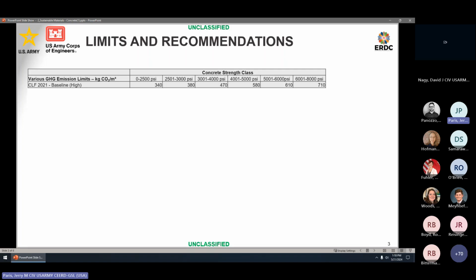So if we look back at the Carbon Leadership Forum for 2021, this generally makes sense. If you're looking at it, as the concrete strength goes up, you typically need more cement. So your limits tend to be higher with the higher strengths, and that generally makes sense. And in this document, they noted that they are treating a baseline as a static reference against which to compare progress towards a goal, which is exactly what we want, right? We want a baseline value, right? Because ideally we're going to go back to that 2005, 2008 timeframe. So having some sort of a baseline to work off of is great.